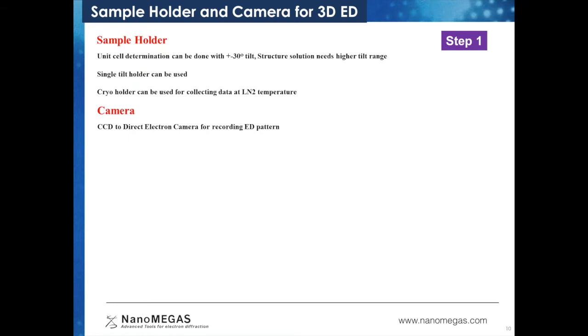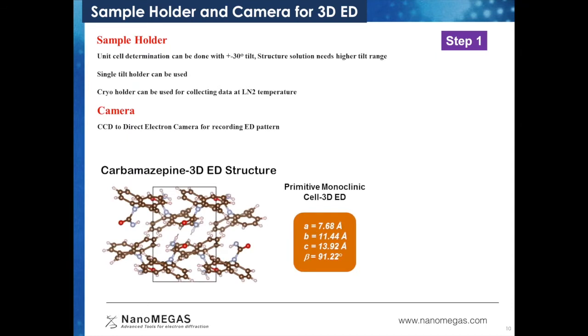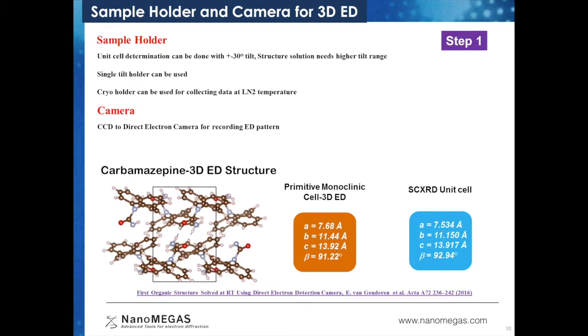In 2016, using a direct electron detection camera for the first time, we solved the organic structures of carbamazepine and nicotinic acid at room temperature. The result obtained by electron diffraction matches perfectly well with single crystal X-ray diffraction data, and this result was highlighted by the International Union of Crystallography. For more details of these results and analysis, you can see the publications mentioned in this slide.